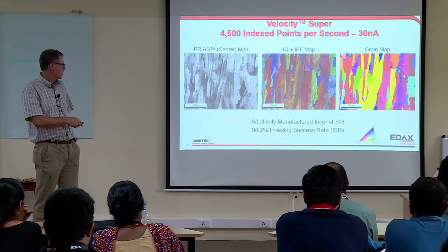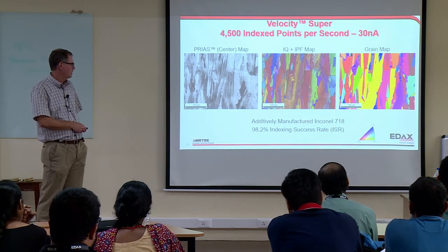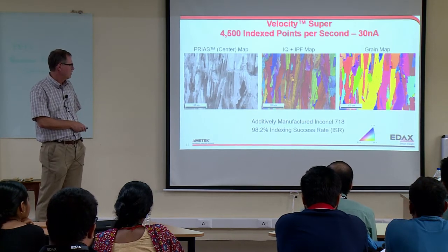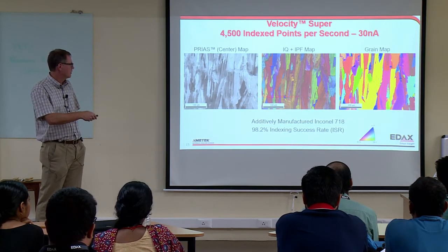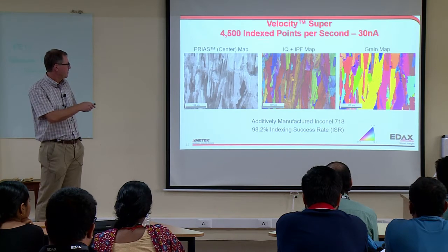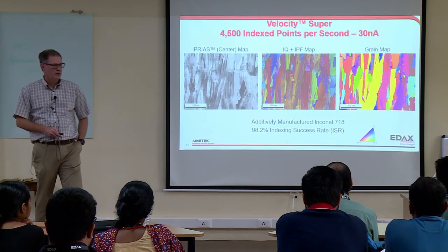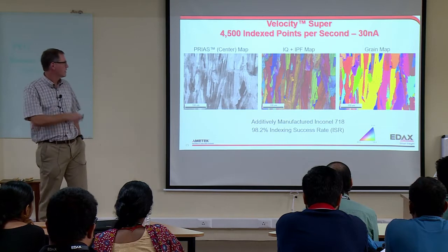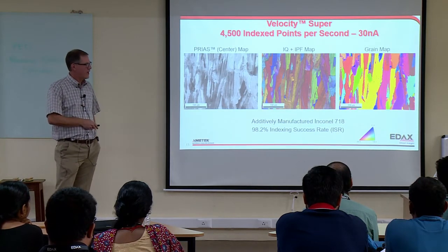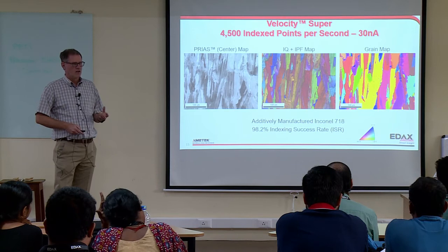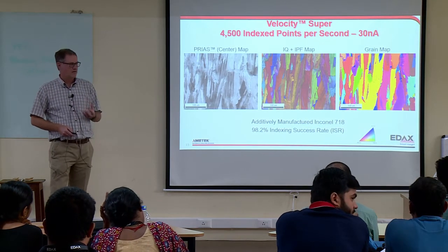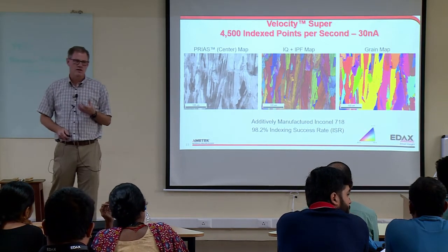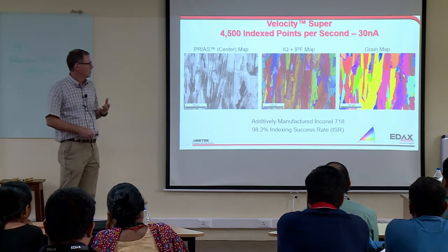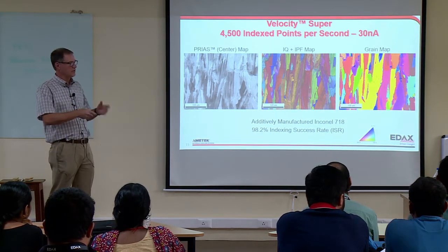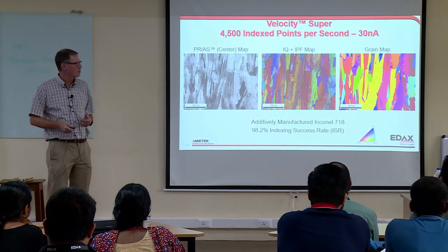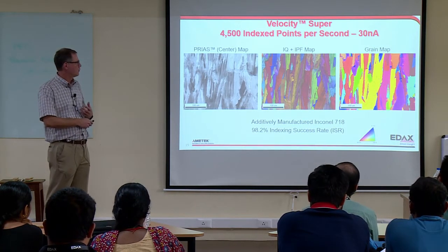Here's something a little more complicated. It's additively manufactured nickel superalloy, but you still see we're getting really good results. The one thing you will notice is that we're operating at a little higher current. We're at 30 nanoamps to get these kinds of speeds. We're going so fast, and we need light from the phosphor, so we're having to hit that phosphor with more electrons to get these speeds. So if current is your limiting factor, this is probably not the best camera for you. Our previous Hikari will work fine.